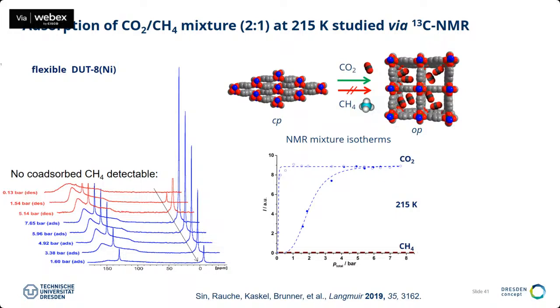Again, here also we explored some in situ methodology in cooperation with my colleague Eike Brunner, where we used in situ NMR spectroscopy, because you can use 13C enriched CO2 and 13C enriched methane to study the selectivity and the selective uptake of these gases. We developed a special cell for static NMR measurements, and here you see basically the NMR measurements of the adsorption curve. And what is very characteristic when you adsorb a mixture of CO2 and methane, here it was 2-to-1 basically, then you see that only the CO2 goes inside the pores.